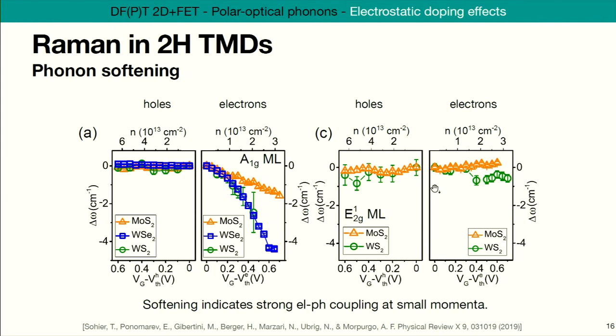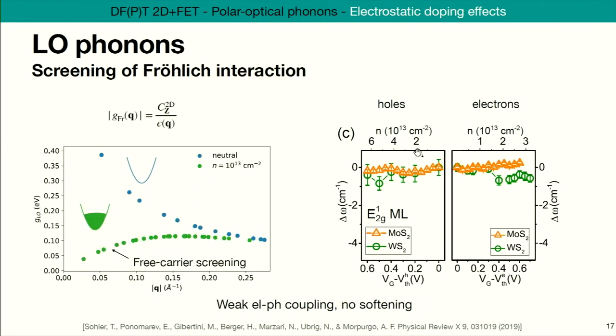So let's try to understand what's happening there. And let's start with the easy case where nothing happens. So this is the Frohlich, the polar optical phonon, where the frequency doesn't change. There's no softening. No softening means no electron-phonon coupling, which can be initially a bit surprising because we talked about this Frohlich interaction and we said that it's rather strong. And I mean, we've seen that it has this sharp increase at small momenta.